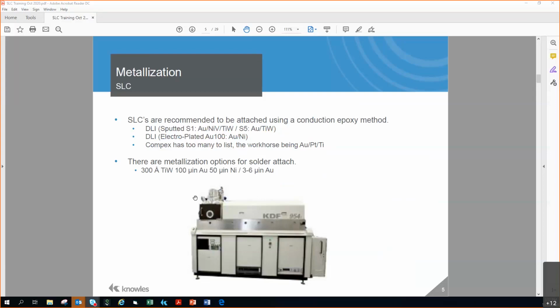Our typical metallization is a tungsten gold. It's that S5 right here. This one, we do S1: gold, nickel, vanadium, and tungsten. Tungsten is always our seed layer. It's the hardest, most abrasive seed layer, so it sticks to the ceramic better. For the electroplated, we do nickel gold. I think it's 50 microinches of nickel and 100 microinches of gold. Seems to be good. We don't really have too many complaints about that.